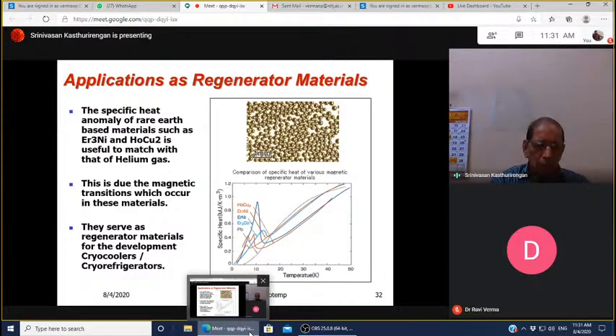Well, in fact, for cryocoolers, which are one of the important workhorses at cryogenic temperatures, these serve as regenerator materials because now the heat content can be stored in these materials, since the specific heat is high. So cryogenic refrigerators or cryocoolers use these special materials for storage of heat content in their body. There are a lot of applications related to that. Yesterday we saw the cryocoolers, GM cryocooler or pulse tube cryocooler, etc. These cryocoolers use some of these materials at extremely low temperatures as regenerator materials, so they are able to produce very low temperatures like close to about 2.5 Kelvin and so on.